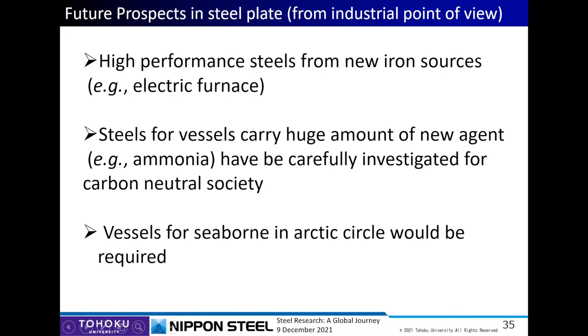Actually, someone has tried to apply almost the same process to electric furnace steel. So in the near future, they can get rid of nitrogen, which is almost the same as the blast furnace. But tin and other impurities are a bit difficult to reduce. For example, tin is not oxidized. We cannot get oxidized tin. So it's a bit difficult. So we have to carefully select the scrap, which has a lower impurity concentration.